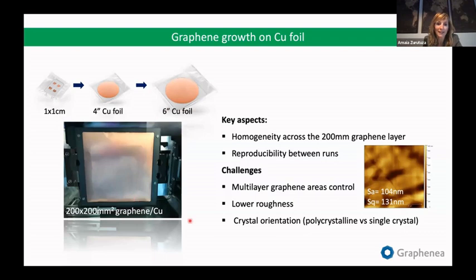What are the key aspects to take into account for the graphene growth? Well, as I said, you want the whole film to be the same, so you want homogeneity, you want all the runs to be the same. Challenges that we face when growing on foils is sometimes at the nucleation point, we have a multi-layer forming. So you want to minimize that. You want the foil to be as flat as possible. The rougher it is, the more defects you can induce there. Another factor is the orientation of the copper. Typically, we use polycrystalline copper foils, but we also do research into single crystal copper catalyst, but not in the form of foils. But okay, I'm not gonna complicate the talk today, and let's stick to the foil.